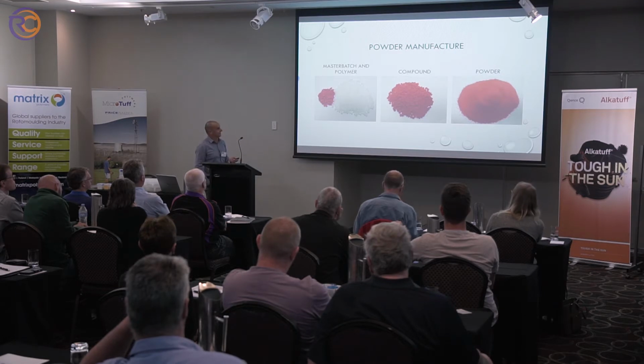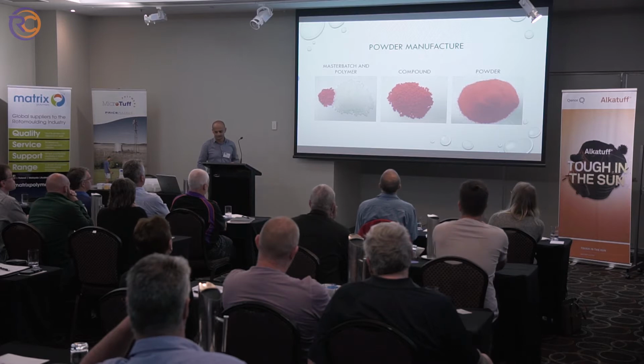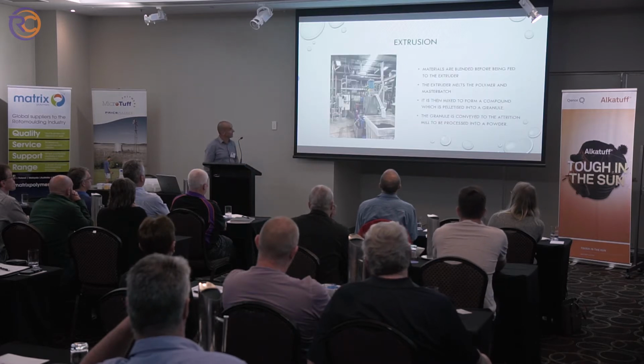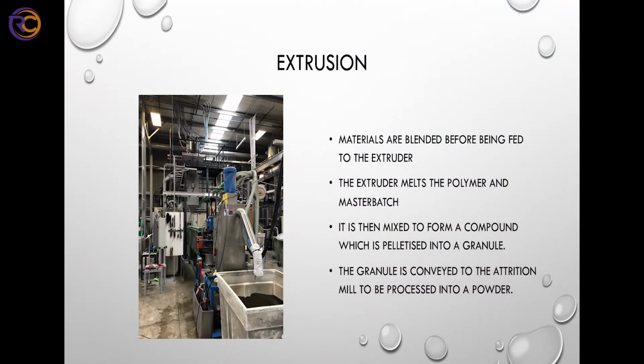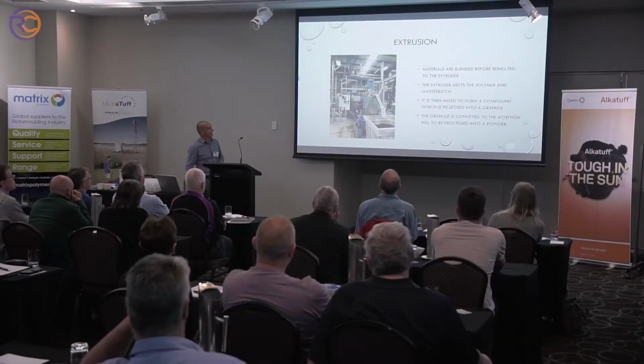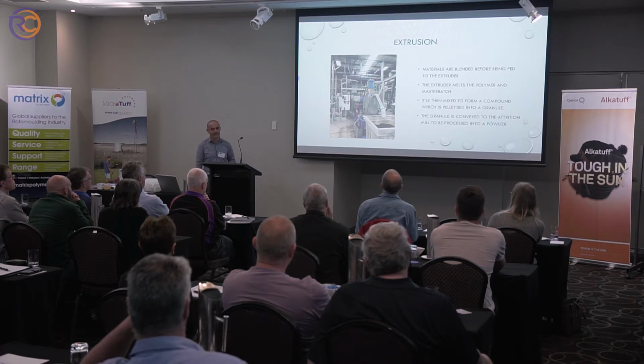So after it's compounded, it comes out in a granule, about 4 or 5 millimetre, and then it goes into a powder which is delivered to you. So, extrusion or compounding. This is a picture of one of our lines. Materials are blended before the feed goes into the extruder. The extruder melts the polymer and the master batch. It is then mixed to form a compound which is pelletized into a granule. The granule is then sent to a grinding machine and it's processed into powder. You can see this machine here is doing black.